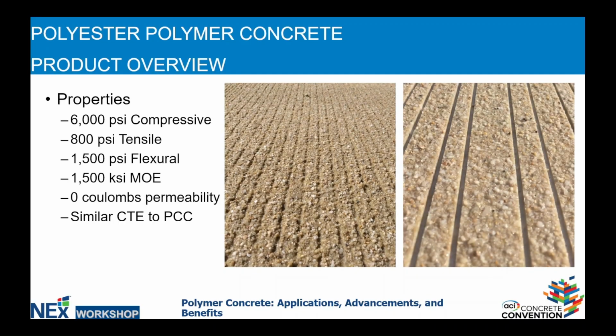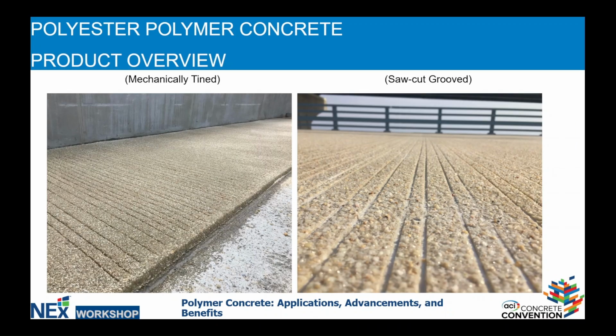You'll see two types in a moment of finishes that we can apply to this type of overlay system. One of those is a mechanically tined finish, which is applied as the material is fresh, still in its uncured state. The tining occurs minutes after it's laid onto the already primed deck. There are other options as well, depending upon what the spec calls for, including a saw-cut groove, once again for the sake of drainage purposes and also providing some additional slip resistance. The saw cuts are typically done 24 to 48 hours after the material has had a chance to be in place and develop its cured strengths.